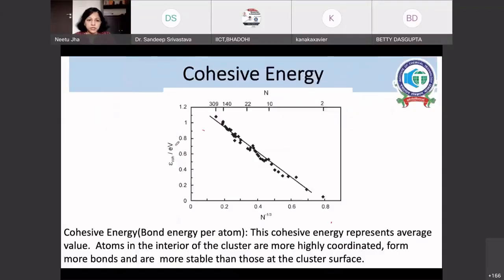And similarly, if we take a look at the cohesive energy, that is bond per atom. Now, as the percentage of surface atoms is high, and these atoms have less coordination bonds and more free bonds, the cohesive energy is also less for nano size particles, whereas for bulk particles, it's more. So here you will get a value closer to 1.39 electron volt, whereas the theoretical value is close to 1.5 something. So the stability of any structure depends on the dispersion. And this dispersion, which is the fraction of atoms at the surface, is very important, from the property variation to the application.